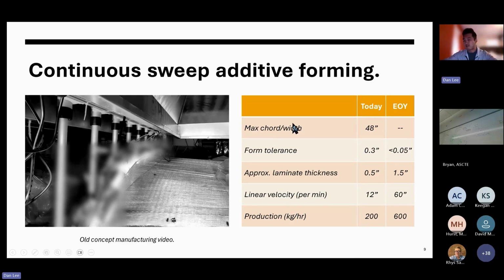The max chord or width is currently limited by the frame of the actuators. We're about 4 feet wide. Our form tolerances are within 0.3 inches. We're working on this, and the laminate thicknesses. These bottom three we have to take together. At laminate thicknesses of 1/2 inch, we're talking about molding levels, so we're about 50 to 55 percent volume fiber fraction. But at this thickness, we can pull at about 12 inches a minute, and that puts us on the order of a production rate of 200 kilograms an hour.